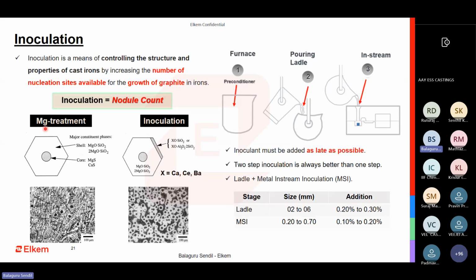I told you to do magnesium treatment. After magnesium treatment, you have a microstructure like this. There are no nodules. You just have carbides, very few nodules. But after inoculation, you have a lot of nodules formed. So inoculation is very important.